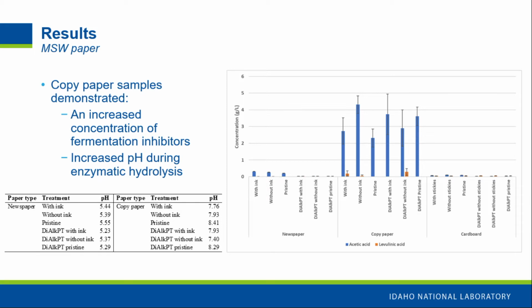And so another thing that we found interesting is that our copy paper samples, so we looked at the different fractions of paper. What we noticed was that the copy paper during enzymatic hydrolysis had an increased level of fermentation inhibitors. So we're not really able to determine the impact of this with our experiments because we were just screening for sugar release. But at a further step down in the process, when we're doing fermentation, these inhibitors really could impact conversion. And so that's something we're looking into now in our further work.